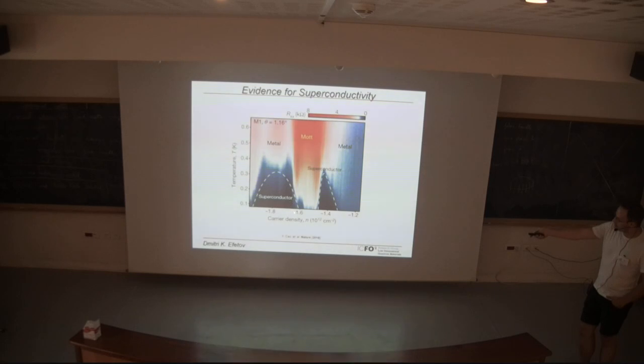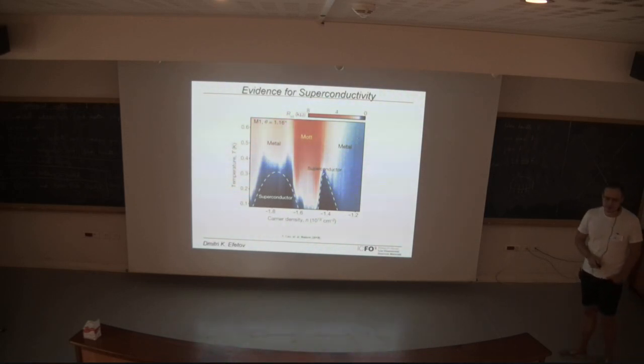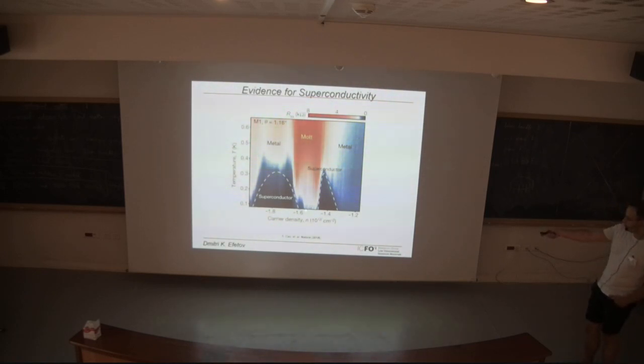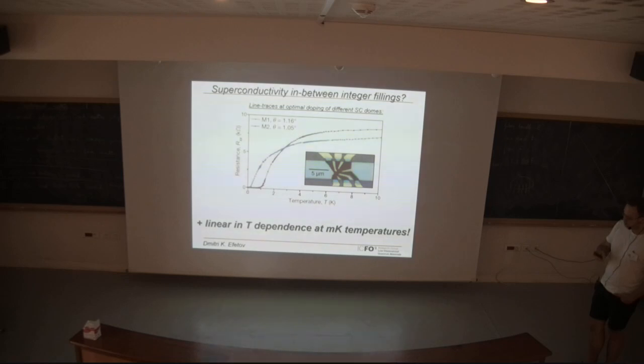That Mott insulating state sits at half filling, or a filling of 2, around 1.5 times 10 to the 12 per centimeter squared. And as you can see, if we now apply a gate and change the carrier density slightly beyond this correlated state, if we move here or here, then regions of really low resistance arise, which is dark blue. And in principle, this resistance really goes to 0. This is data from Pablo's paper.